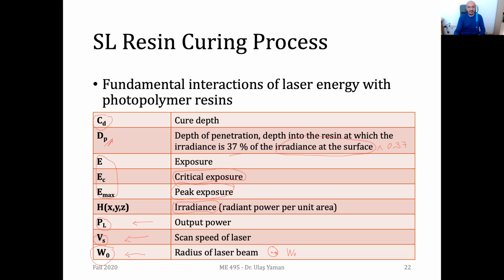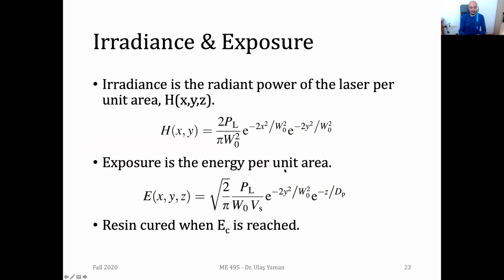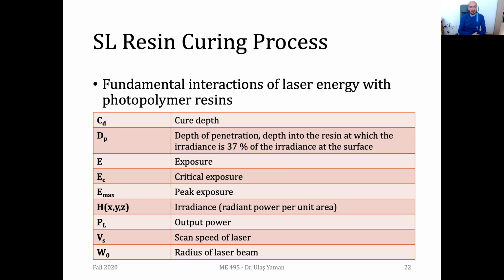And we have some parameters related with material, for instance, this critical exposure. This highly depends on the material. For instance, if you have a difficult to cure material, then that means its critical exposure value should be higher than ordinary materials. And another thing, depending on the material, is the depth of penetration and the curing depth. We will talk about these on Thursday. We don't have much time now, so I don't want to start the modeling. We will be discussing it on Thursday.